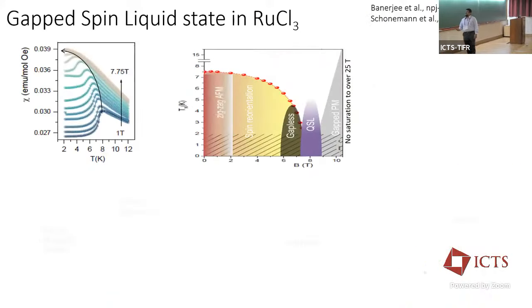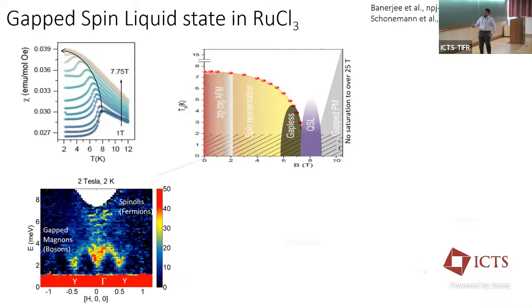So in order to see what happens, we applied a field. First, it was easy for us to apply a field in plane. It's just the experimental constraints. What we find is that at 8 Tesla, you not only kill the long range order in ruthenium chloride, but you basically go through a transition. At low fields and low energies, you have these magnons, the parabolic-like states I told you about, sitting on this continuum of spinons, which is this cloudy feature here.